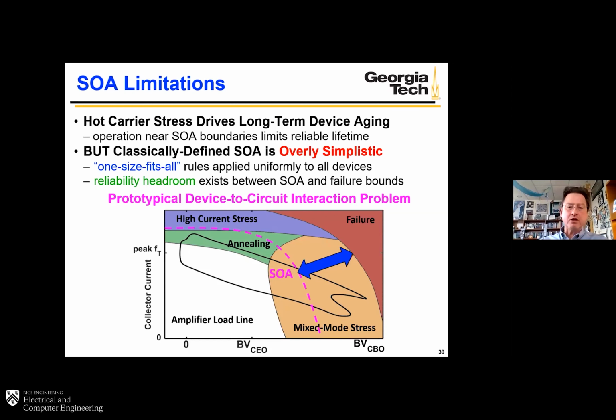I've superposed there a dynamic load line as a device is switching inside a circuit, just so that you can see this. But the first thing to say about the silicon-germanium picture is that the damage space, the aging stress space, is nuanced and complex. And you see 4 different regions where bad things can happen. You have mixed mode stress, which is typically high voltage, medium-sized currents; high current stress, which is low voltage, very high currents; an annealing region in between; and then ultimately the hard fail limit out on the right-hand side that could either be electromigration induced or just junction induced.